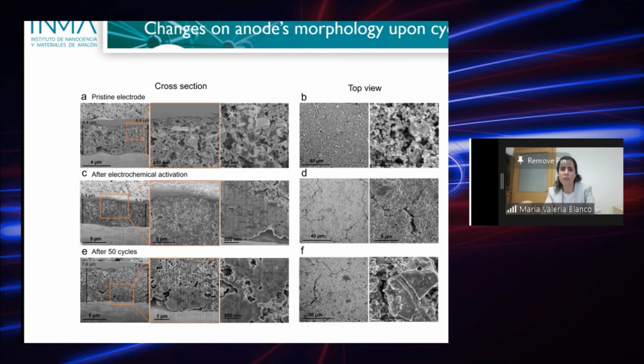And on the right hand, you have a top view of the anodes, and you can see also that after activation and after the galvanostatic cycling, we start to see some cracking of the surface of the electrode, which also means that there is some issue with the volume expansion of silicon that is little by little affecting the morphology of the electrode. Even if we are not able to see this in the electrochemical data because it looks quite stable, this means that in the long run, if we make more cycles, we will have the effect of losing some power because of these volume changes of the silicon.